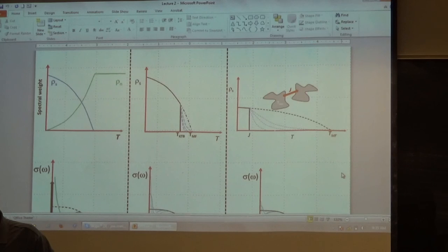It's certainly not due to just the gap alone, right? That was the controversy way back when. Since you're getting the paramagnetic term to go away, the simple-minded view would be that you have that degenerate perturbation theory sum, and you have an energy denominator. The numerator goes to zero, and the denominator doesn't, so it goes to zero. Then people said, wait a minute, that tells me that anytime I have a gap, I'm a superconductor. So from the perspective of BCS theory, the reason it actually works is that although you have this buildup of states and you conserve states, the matrix elements vanish at threshold. And that's the crucial argument that gets it to be zero, even in the case of the dirty superconductor.